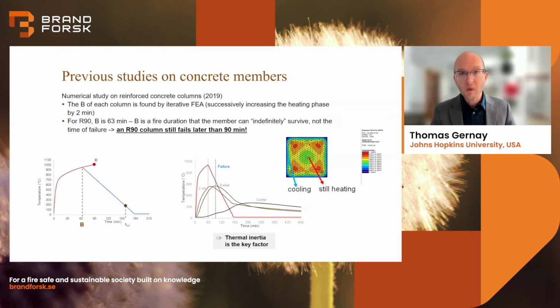It's important to re-emphasize that this burnout resistance is shorter than the fire resistance. That does not mean that the column would fail earlier than the 90 minutes. In this example, with the burnout resistance of 63 minutes, failure occurs later than 150 minutes. So here we are characterizing the ability to survive to full burnout. We are not characterizing the time of failure. So again, a column characterized with 90 minutes of fire resistance would fail later than 90 minutes when subjected to the ISO 834 curve. That is clear.